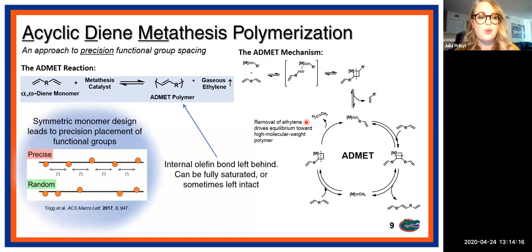So we can design our monomers so that they lead to the precision placement of functional groups. So if this alpha-omega-diene is perfectly symmetrical, that will result in precisely spaced functional groups as seen in this figure here. The alternative would be if the functional groups were randomly placed along the backbone. We can prepare this too, but that's generally not the type of materials we're interested in. And as I mentioned, the internal olefin bond is left behind. And generally we go on to fully saturate the backbone, but in some instances we leave it intact if it is necessary for whatever we're looking at.